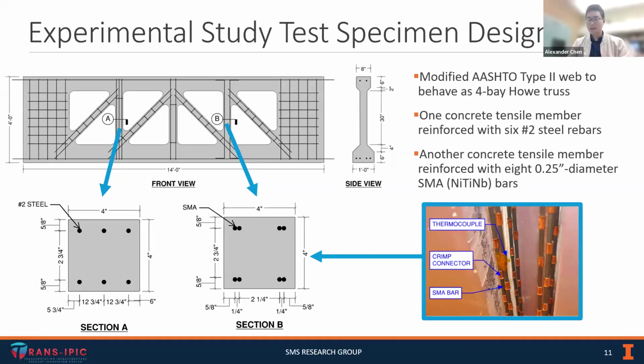Here's an image of what these SMA bars look like before they're placed inside concrete. You'll notice they have a smooth surface, so what we did was add these copper crimp connectors along the length of the SMA bars, and that's going to help it engage and bond with the concrete. We also have a thermocouple attached, and we'll be using that to monitor the temperature of the SMA when we heat it up.